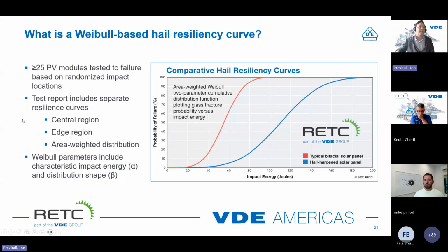And so we will do that in the center region and the edge region, which has different glass breakage, different strengths essentially, and then we'll weight the results of those tests based on the areas of both of those regions to come up with a Hail resiliency curve that we use for modeling.